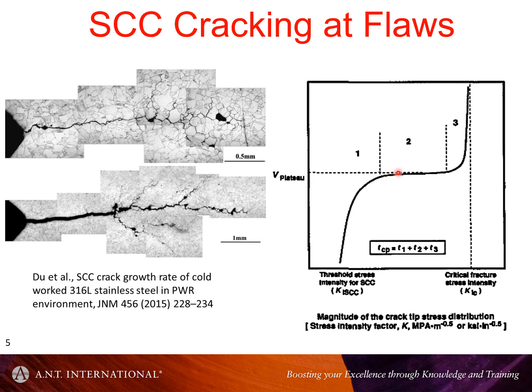So just like with delayed hydride cracking, the issue with stress corrosion cracking is what is the point at which we initiate, if we're in a condition where we've exceeded initiation, and then once you're in initiation, what is the rate, how quickly does it progress, and eventually the thing that you want to avoid is actually getting into the critical crack length point where the material will just crack anyway, catastrophically.